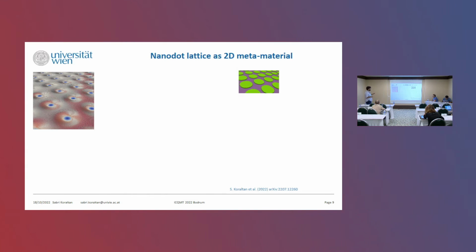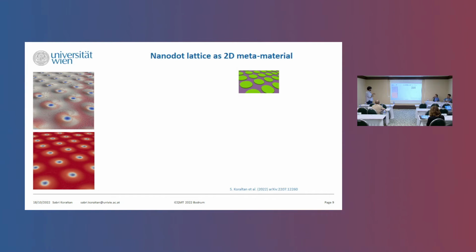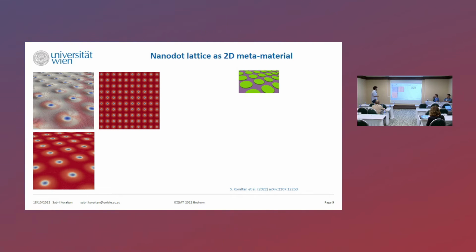And experimentally, one can achieve this by heating. Permalloy and the iron gadolinium multilayers will have different Curie temperatures. So if you heat it up only to, let's say, 400, 500 Kelvin, then the permalloy will still be ferromagnetic, but iron gadolinium will already become paramagnetic. So then you can manipulate at high temperatures. You could manipulate the permalloy disks, arrange them all in a clockwise manner by applying an x field, and then apply a positive field, and then also decide over their polarization. And then cool back down, and then obtain a full lattice of skyrmions.